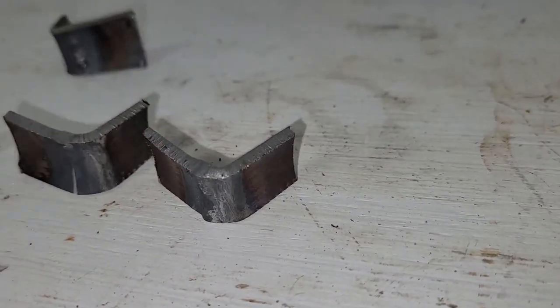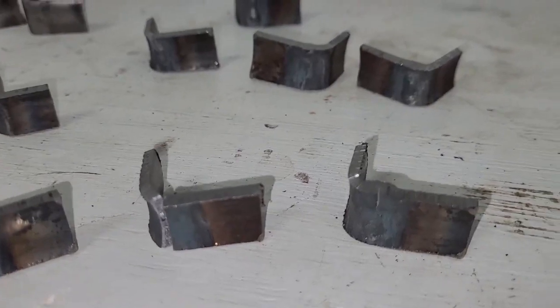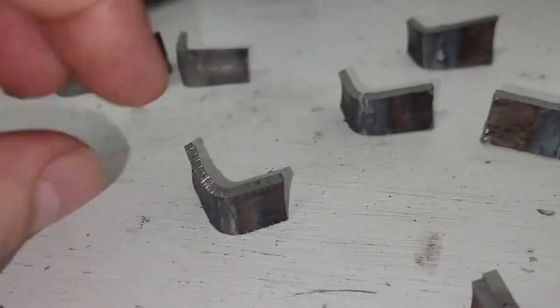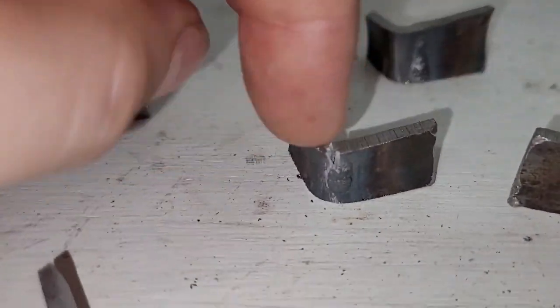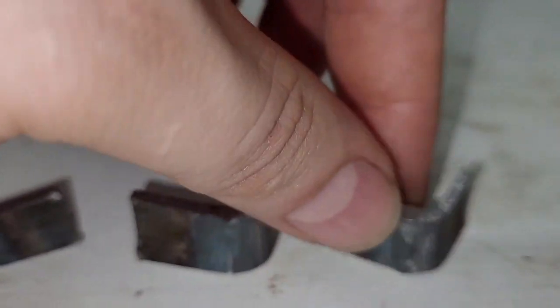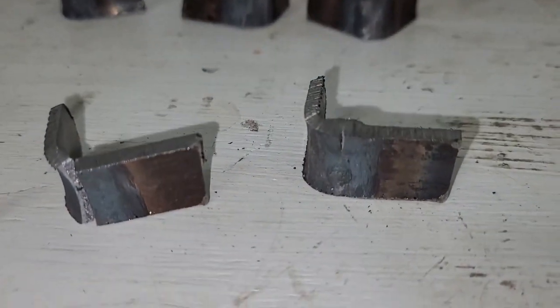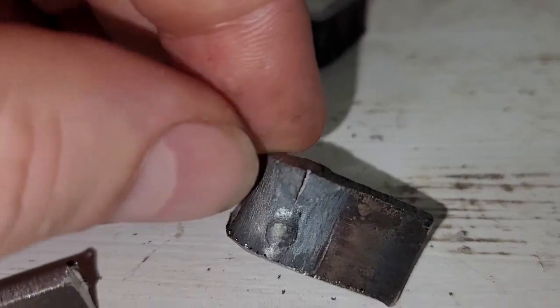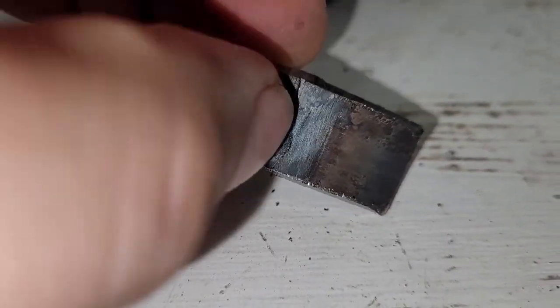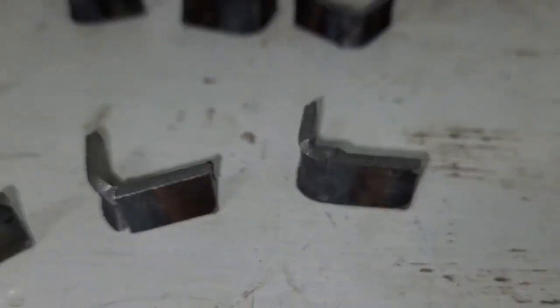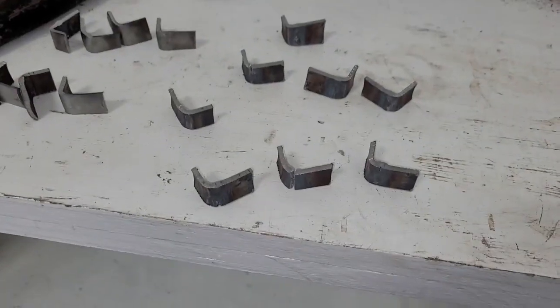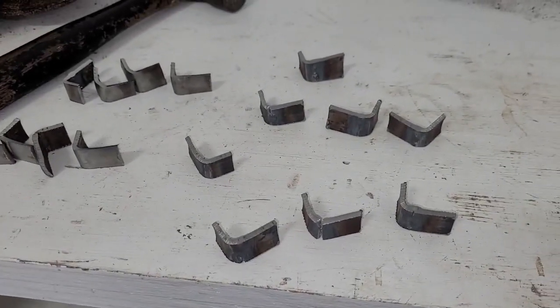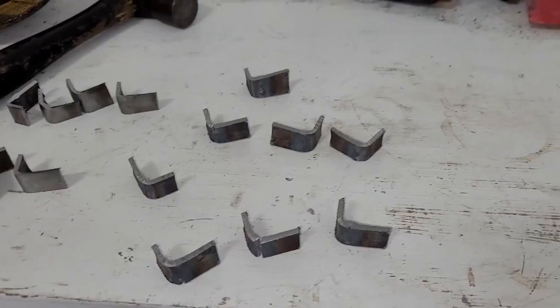And I bet every single crack started from an edge, because that edge is just under so much tension. Let's see, that one started from an edge. Yeah, that's every single case that started from the edge. So that's really not surprising because we're just putting a tremendous amount of stress from that being a curved surface. So that does make it harder to pass, but it's also easier to do testing this way. But thought I'd point that out.